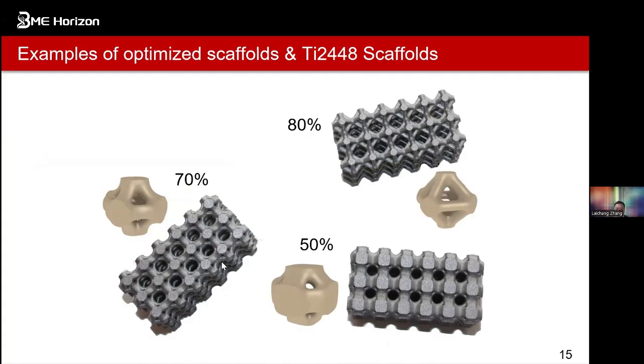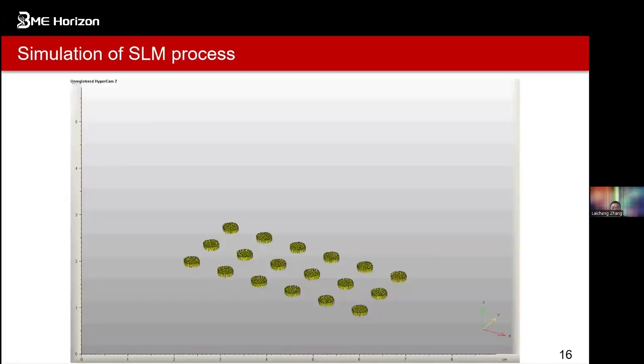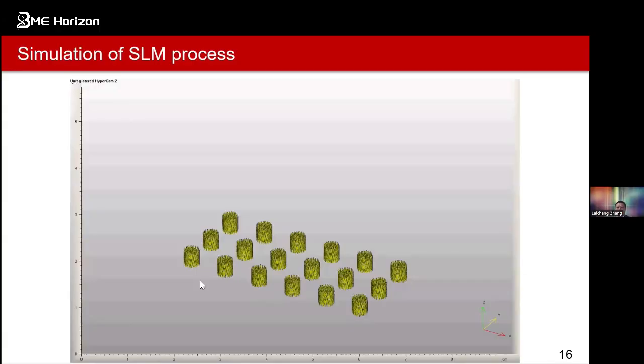And this is the way, for example, to show the structures. You can see the parts we produce are 3 by 3 by 6, so we can produce many things like this. Of course, this can go up to 95% porosity, which means only 5% solid fraction. So that is a very high porosity structure. This structure is very complicated. You can see the support, and every layer is complicated and different. This simulates the 3D printing layer by layer, that is, additive manufacturing layer by layer. We can see the structures of these things.